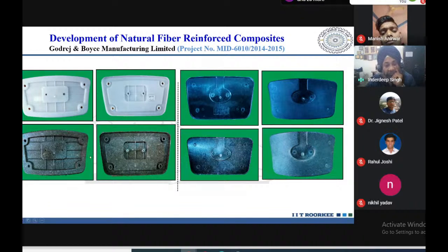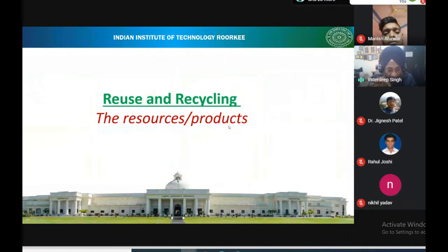And these are the modified products with 30 weight percent of sugarcane fiber. And this is the back part of the chair. Now this is the first part, that is reduce. Reduce means that instead of using 100% polymer, we can use 60, 70, 80% polymer, and at least 20-30% can be coming from natural sources, which are otherwise classified as agricultural waste or sometimes forest waste also.